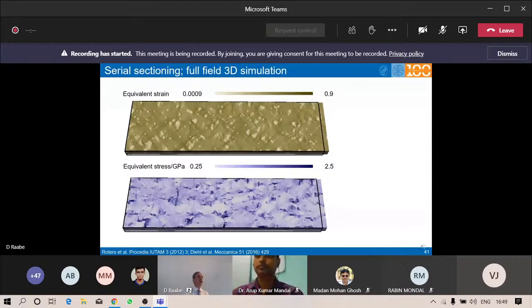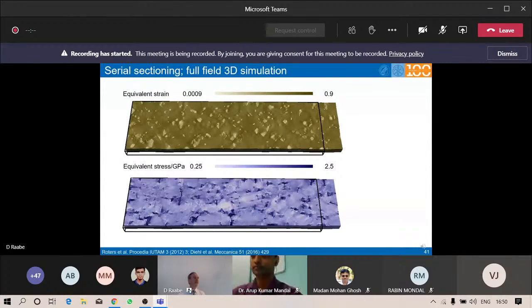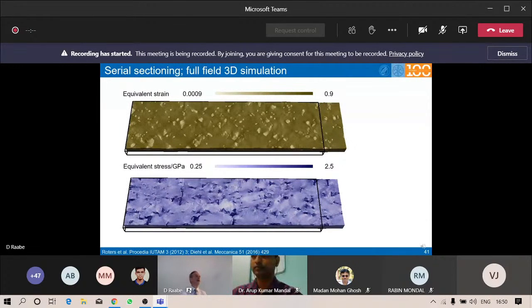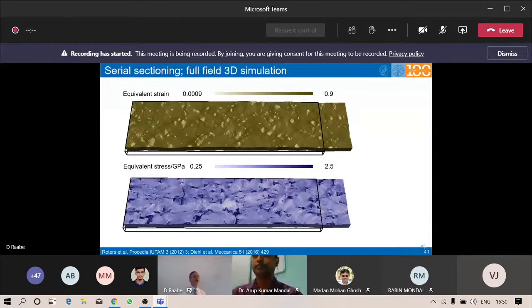And you see here now the corresponding computer simulation where this is uniaxially loaded. And you see the equivalent strain and equivalent stress distribution that arises. And when you compare that in detail step by step, like I've shown before, you get a much higher fidelity of the reproduction of your measurable surface strains due to the fact that you really account for the microstructure layers that you have also below the surface, which, of course, affect the surface stresses and strains.